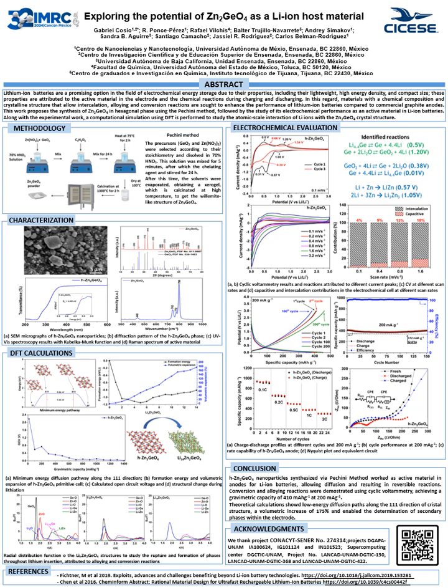yield a white powder. The powder was characterized using scanning electron microscopy, X-ray diffraction, UV-vis spectroscopy, and Raman spectroscopy. The results confirmed the hexagonal phase of the material, its chemical composition, and a band gap of 4.49 electron volts. Once the desired material was confirmed, it was utilized as the active material in electrodes for coin-type cells.